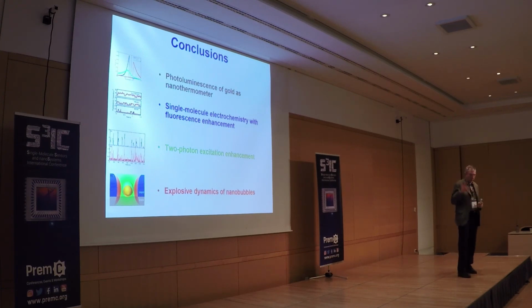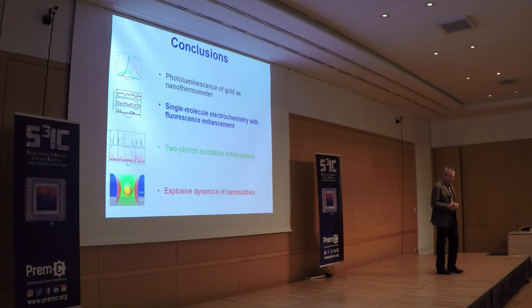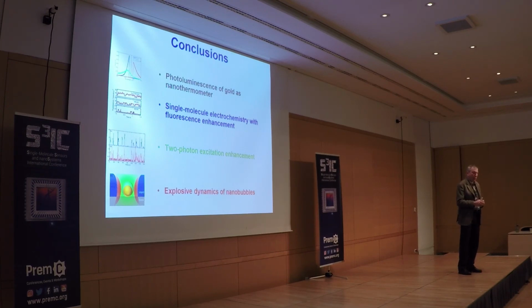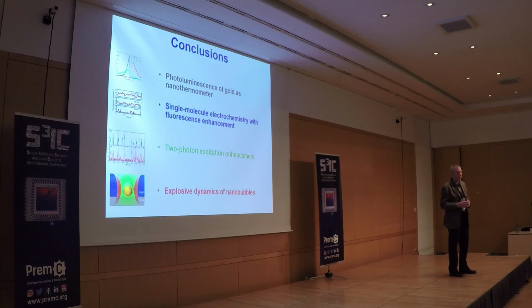Yeah, so this is a question about the electrochemical cell that we used. Of course, we can do this experiment in different ways. We are not electrochemists, so we discuss with colleagues. What we do in this experiment is very simple. We minimize the volume of our cells so that we don't have a long diffusion time. So typically, we waited a minute to have a stabilization. And all the measurements I showed you were done at a fixed voltage, and you measure statistics of these on-off times. Then you change the voltage, you wait one minute, and you measure again, change the voltage, measure again. And you do that for every single molecule. The long part of the experiment is to find the single molecule close to the nanorod. Once you have done that, the molecule is stable for at least several minutes, especially in the dark when you don't measure. So you have time to vary the voltage, and for each voltage to acquire a trace.